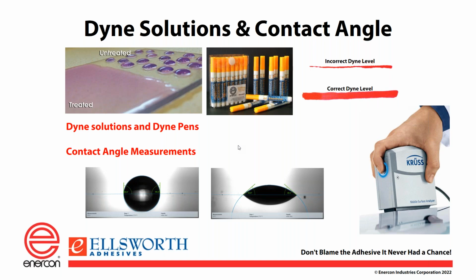Contact angle is a little more accurate. We use it in our lab every day to get better information. In this case, you're actually using two different materials, a polar and then a dispersed energy unit, to measure the surface energy. And once you've treated, hopefully the first slide there is pre-treatment. So with contact angle, you'll see the water is beading up on the surface. And then the second image there, after you've treated, you can see that it flattened out. And so the water is spreading out, similar to that picture of the treated slide up top. So that's how we measure those.